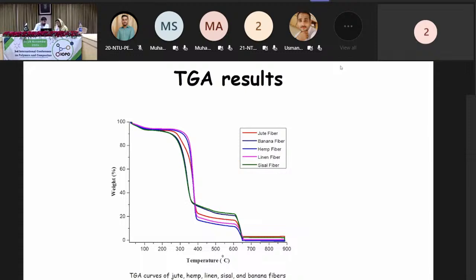Regarding the TGA results, the test consists of 4 stages. The amount of mass retained as temperature rises is shown in the graphs as weight percentage. For jute, hemp, linen, sisal, and banana fibers, weight reduction in the first stage was 6.9%, 6%, 5.6%, 6.7%, and 6.4% respectively. All natural fibers exhibit this tendency as a result of present moisture.